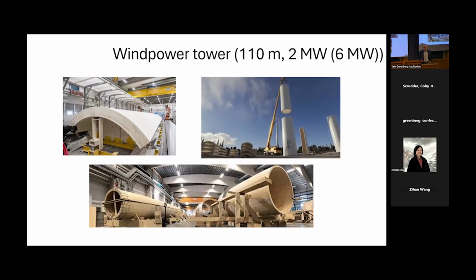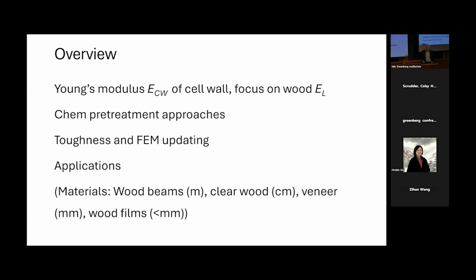This is very promising technology. There's one unit up and several in the pipelines. I will focus on modulus, trying to understand the modulus of these materials. The reason I will not talk so much about strength is that it's very difficult to use strength as a material property. If you look at the bottom there, you see that we have many scales, and the strength of a given material will be different if we measure the strength of a beam or of a wood film, for instance. So that's why I focus on modulus, which is easier to predict based on fundamentals.